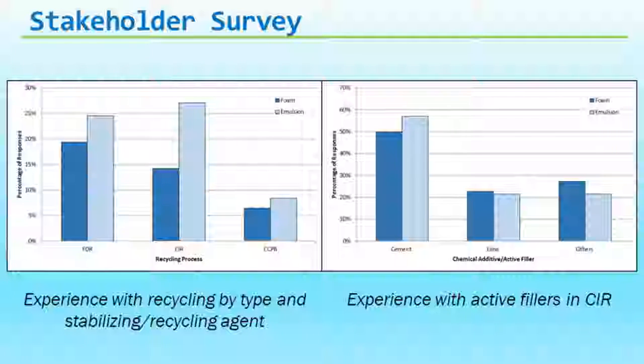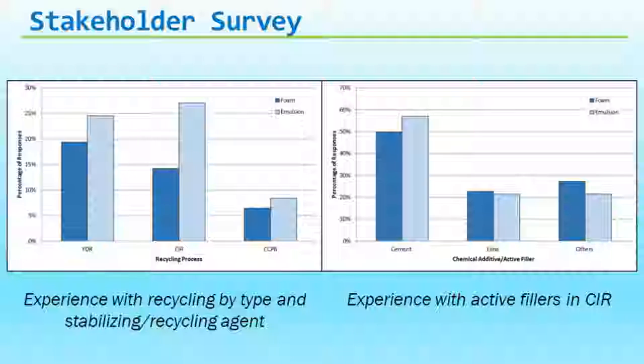Some other interesting information is experience with the recycling type. Dark blue is foam and light blue is emulsion. On the left is full depth, in the middle CIR, and on the right CCPR. You can basically see that most people have more experience with emulsion than with foam. And for experience with active fillers, same colors: on the left, cement, in the middle, lime, on the right, other. You can see cement is definitely the most commonly used active filler out there.